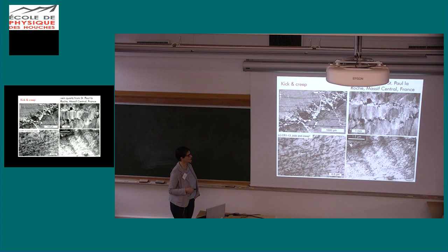So we also probably nucleate further dislocations, so that we end up with these deformation lamellae or areas of increased dislocation density that alternate with areas of lower dislocation density, although in this natural example, where we have these dislocation walls, this is not an area of low dislocation density, it's just a different diffraction contrast.